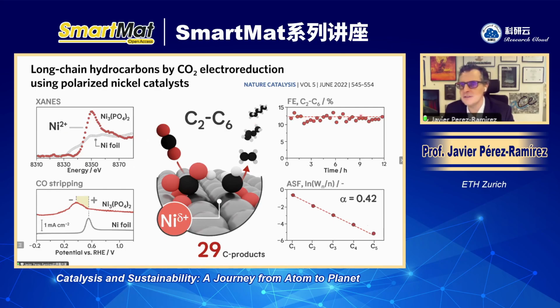You can see here the Faraday efficiency to C2 to C6 hydrocarbons, right? And this nickel 2+ is actually responsible for the coupling ability of this catalyst, which follows an ASF distribution typical of Fischer-Tropsch with C1, C2, C3, C4, C5, up to C6 products.